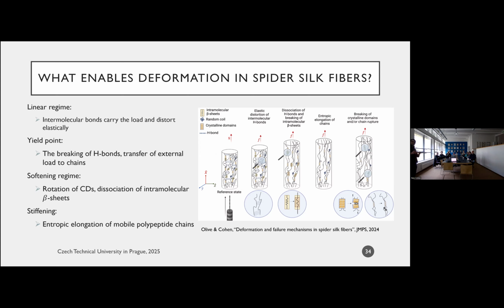So this is a pretty weird situation. We have chains that initially feel very little force, right? We have chains in the initial state. When I start stretching it, the chains don't feel a lot of force because all of the force is carried by the intermolecular bonds. Once these intermolecular bonds break, all of the external load gets transferred immediately to the chain. And now a chain which was initially under very little force, all of a sudden feels this huge force that's being applied to it. Because of this, chains extend, right? So that gives us this kind of softening or jump-type effect.